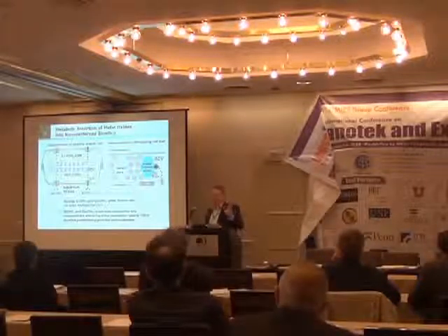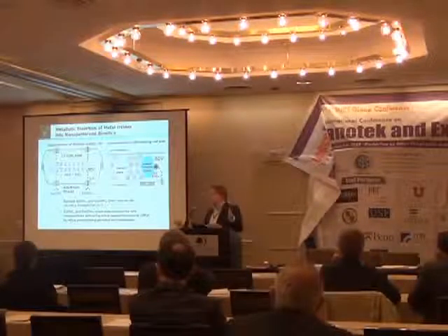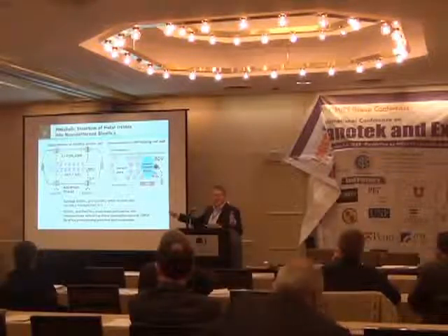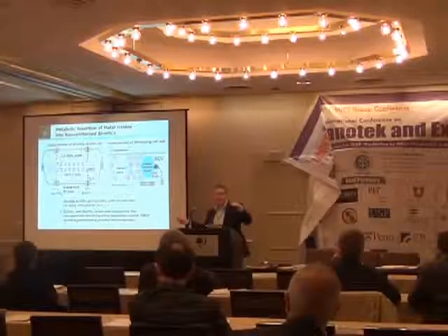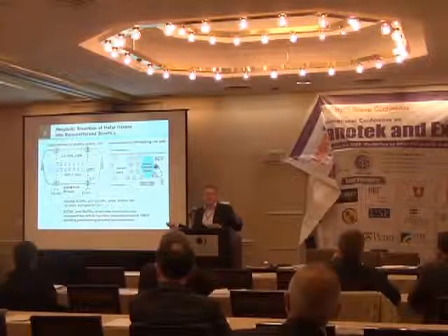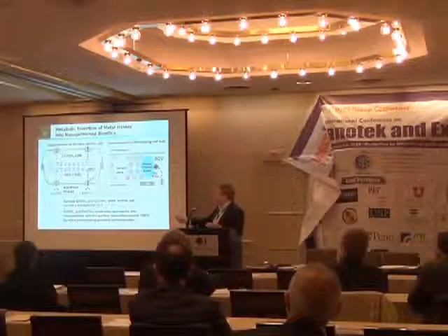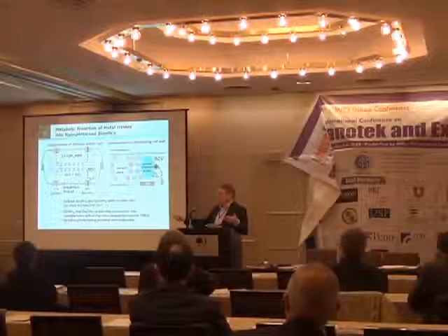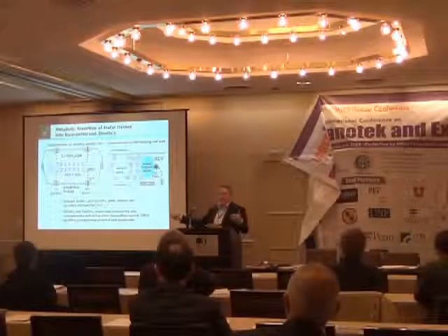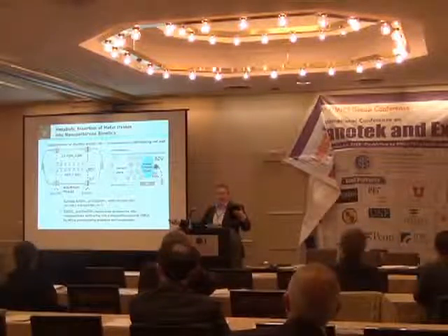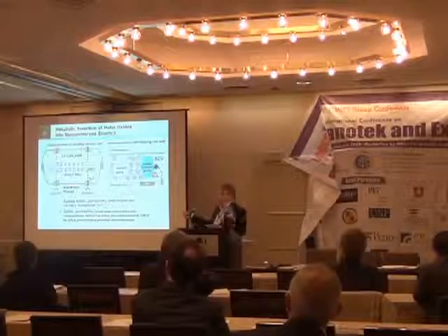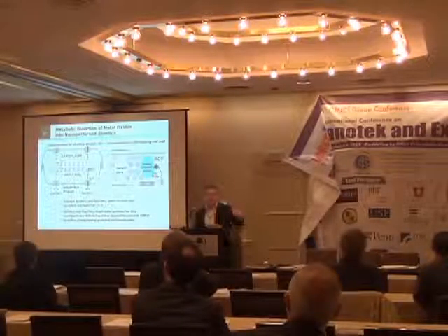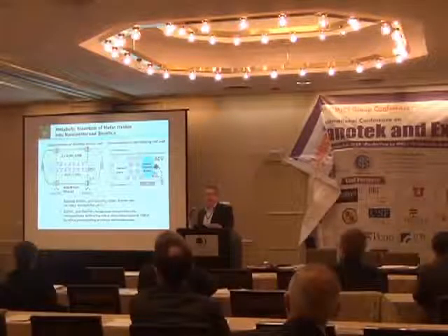Briefly, when the organism is about ready to divide, it forms a plane of cell division, and on either side it sets up an organelle that orchestrates fabrication of the nanostructured metal oxide phase. This organism can work against a concentration gradient — it has a silica transporter built into the cell membrane which pumps in soluble silicon, or in our case a foreign substrate, soluble germania. This material is then polymerized into nanoparticles based on an organic template phase within the deposition vesicle, allowing foreign metal oxide nanophases to be embedded within the silica matrix.